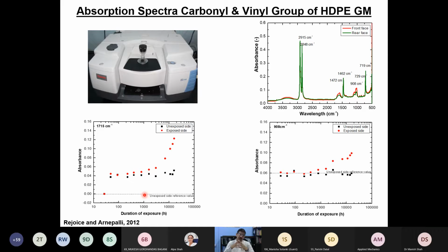In order to capture the molecular level changes in terms of their functional groups, we used FTIR, the Fourier transform infrared spectrometer. We tried to see how the absorption spectra vary between the front face, which is the exposed face, and the rear face, where there is no exposure. At a given absorbance value, for example around the wavelength 1715, if in the exposed area this absorbance value is increasing, that means something is happening to the polymer at these regions.